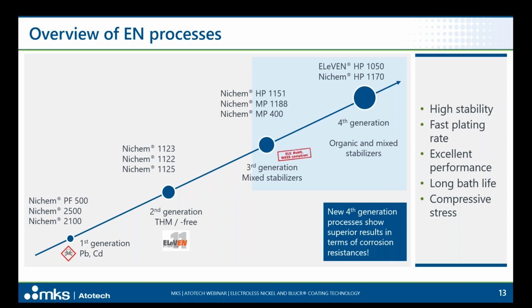And the last generation of organic and mixed stabilizers with the ELeVEN HP 1050 and HP 1170, with an excellent performance regarding the plating rate, stability, the bath life, and also a very low compressive stress over the bath life. Also, it's very important to mention that this last fourth generation shows very good results in terms of corrosion resistance.